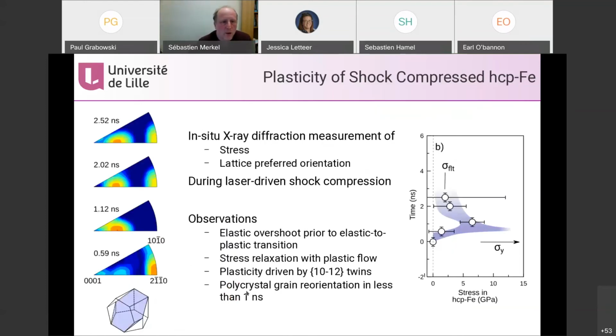So in terms of plasticity of shock compressed HCP iron, we managed to perform in situ X-ray diffraction measurements of stress and lattice preferred orientation during laser-driven shock compression, and look at the time dependence of stress and of microstructures. One limitation is we are shooting X-rays through the whole sample. We're not looking exactly at the shock front.